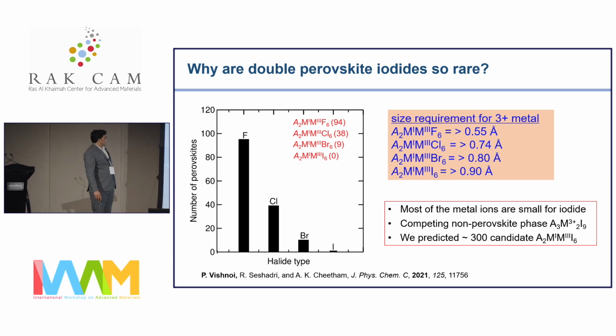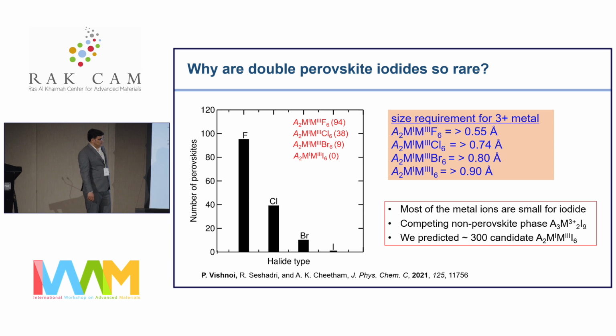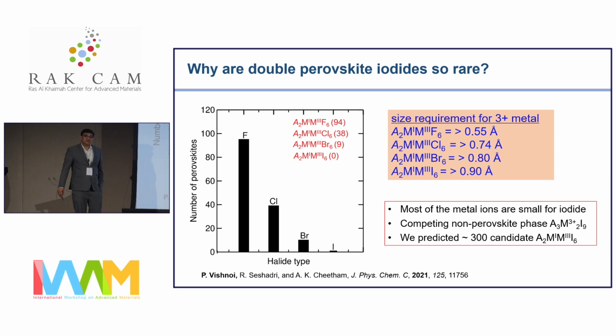Here I also want to mention that methylammonium lead iodide is a monoperovskite with so much interest, and this has a narrow band gap. But as Professor D.D. Sharma mentioned, there is instability and a lot of issues in that, and people are looking at other alternatives, including low-dimensional 2D systems and so on. But one of the alternatives that people are looking at is the double perovskite iodide. And there's a massive amount of interest in that. However, there was no iodide perovskite known. So it is important, to boost the discoveries in this area, that we give a model which can tell why it is absent, despite the fact that there's a lot of interest in that.